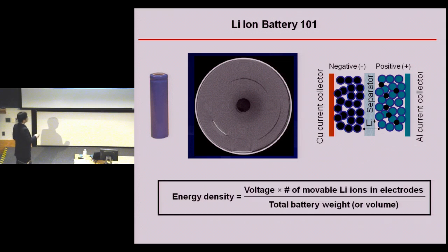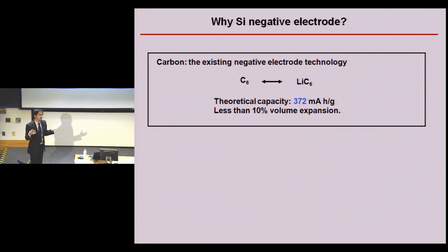So the energy density, one of the key parameters for this kind of energy storage device, depends on the voltage difference between the positive and negative electrode times the number of ions that you can store inside the electrode, normalized by the battery weight. So that's the reason why carbon is widely used, because carbon is a very lightweight material, and it has a theoretical capacity of 370 milliamp-hours per gram.